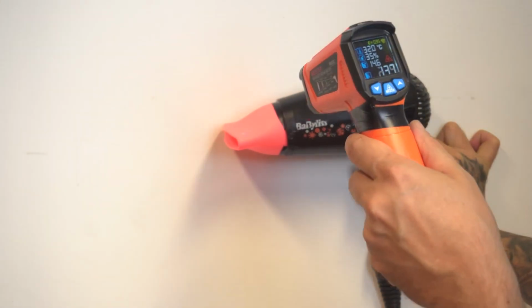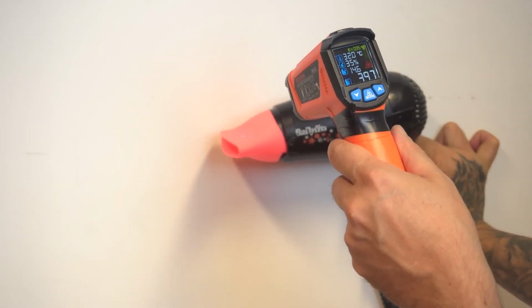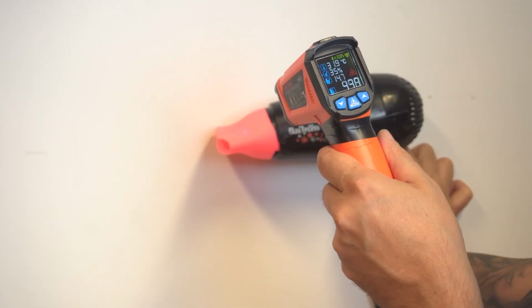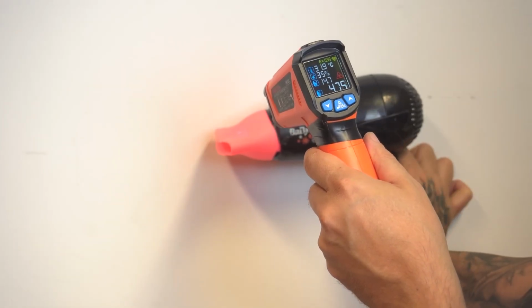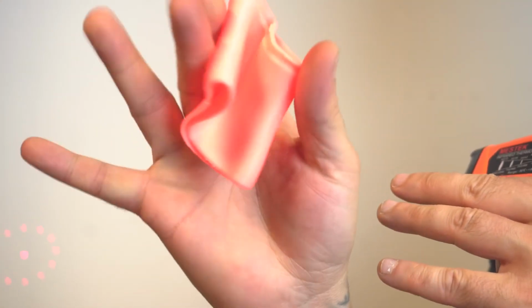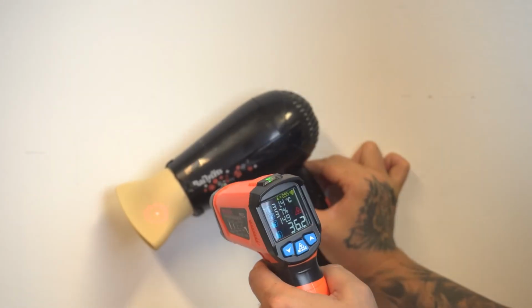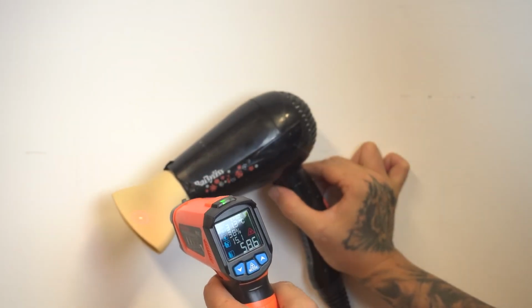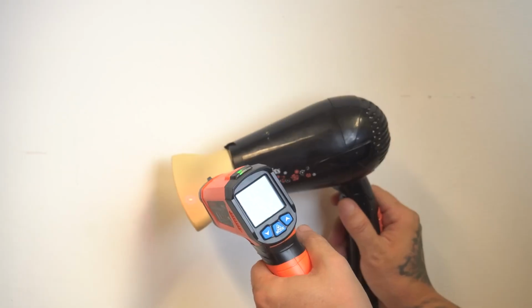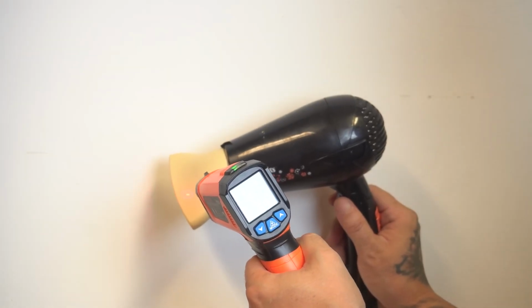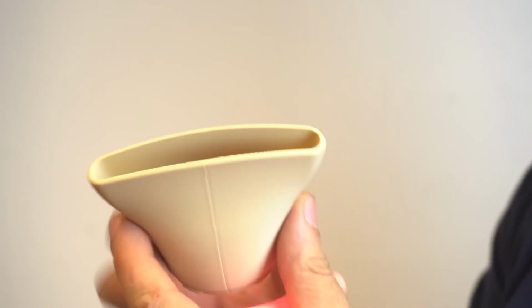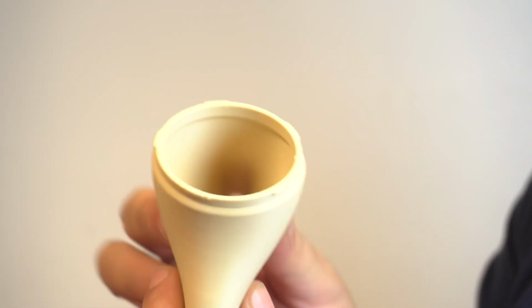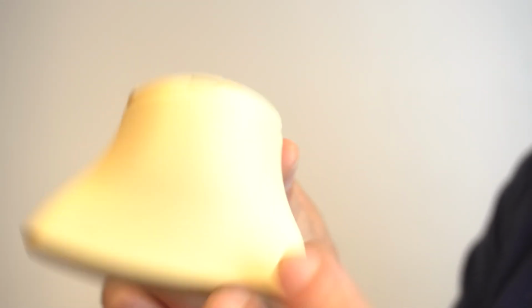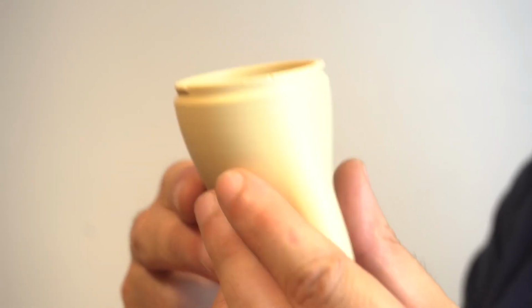And for the hairdryer test, we can see the tip of the hairdryer going down around 60, 65, 70 degrees Celsius. It was a little bit difficult to catch the temperature correctly, but we got it. And you can see it's really soft, almost melted, and yeah, the shape is completely gone. And for the HT-PLA, again, around 75 degrees, 70 degrees, again, was really difficult to catch the temperature like that, but we got it perfectly. Still preserving its shape, no deformation, nothing whatsoever, same hardness, same shape as the beginning.